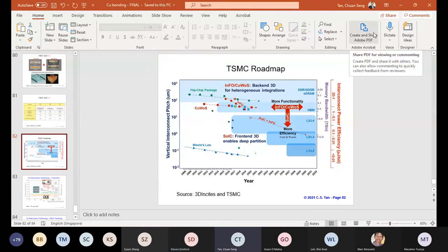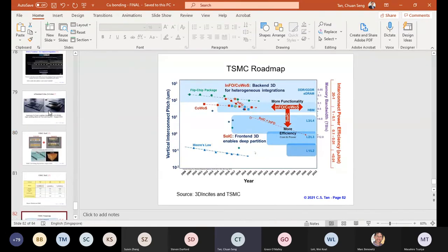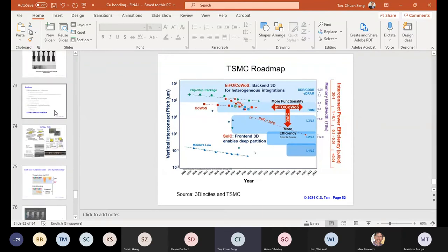Well, we basically wrote a paper back in the mid 2000s or so, talking about the origin of the void. And I think we know why. That has to do with roughness, particles, dishing and all this. But my number one concern when you have voids is that they will accelerate the electromigration issue. So that is my answer to you. I think it has to do with reliability. It will certainly accelerate your reliability concern.